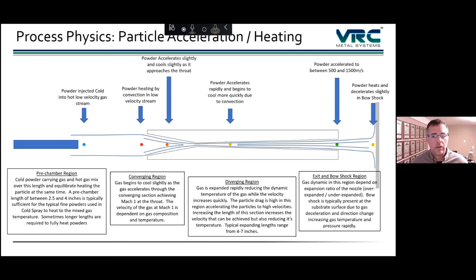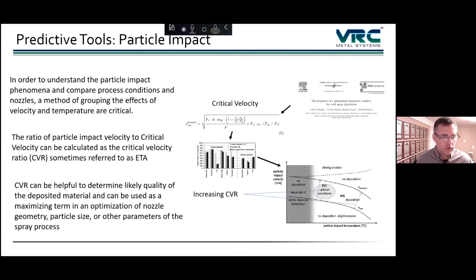So in order to better understand this process, we can figure out what the velocity and the temperature of the particle is at impact, but we need some way of rationalizing what that does during consolidation. So there's been some work in doing this. This is an example of some work done by the Helmut Schmidt University to come up with a critical velocity number. This is a semi-empirical formulation that does a pretty good job with a lot of different metals, especially pure metals. So it gives you a sense of how the particle velocity and temperature affect bonding of that material.